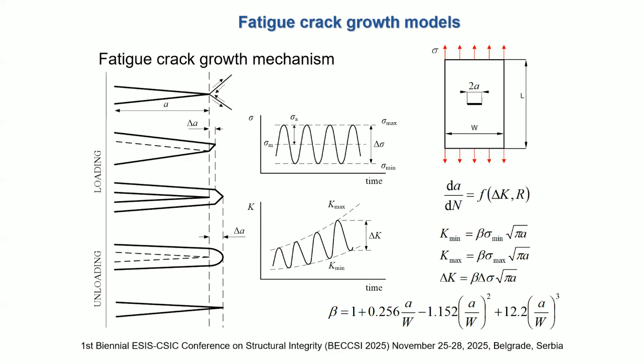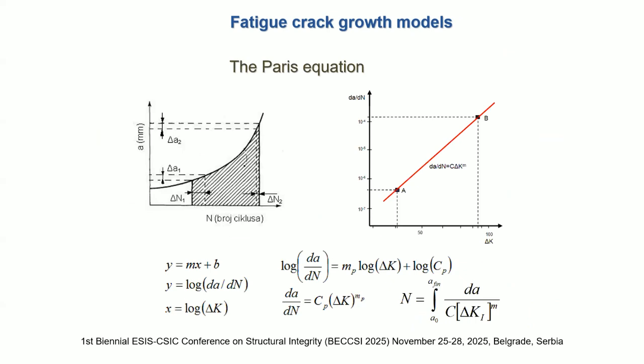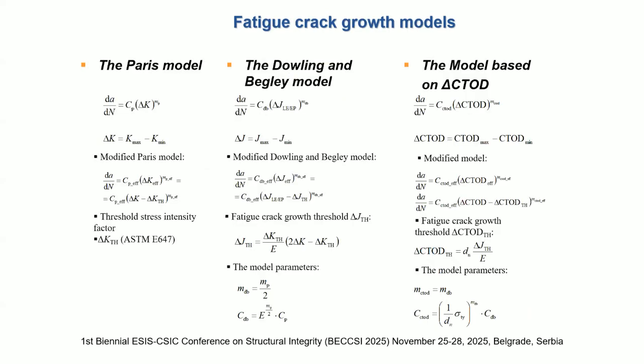And this is our specimen P1 with 1 central crack. And to simulate this, we can use Paris equation, but we need stress intensity factors. So they can be calculated analytically, but it's better to calculate them numerically. And from crack growth rate diagram on the right side, we can obtain this equation here, which is called Paris equation. And if you write this equation in another way, we can calculate number of cycles needed to propagate from some initial crack length to some final crack length. And this is very fine, we all know this.